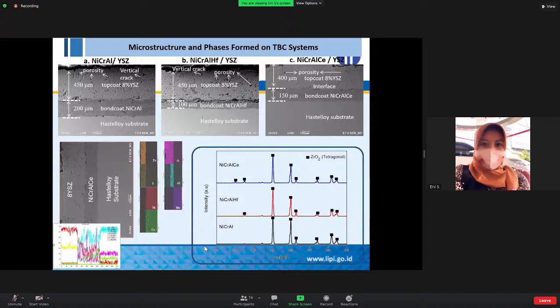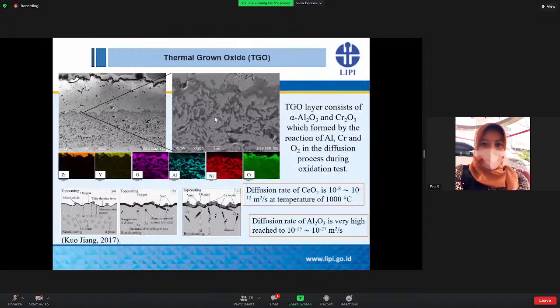By using the phase analysis, it is mostly composed of zirconia phase with tetragonal structure. It revealed that 8% yttria stabilized zirconia could withstand the formation of the zirconia phase with the tetragonal structure. So we try to enlarge, as you can see in this figure, the layer, which can consist of alpha alumina formed by the reactions of aluminum, chromium, and oxygen in the diffusion process during thermal treatment.